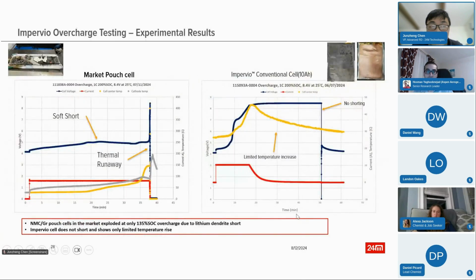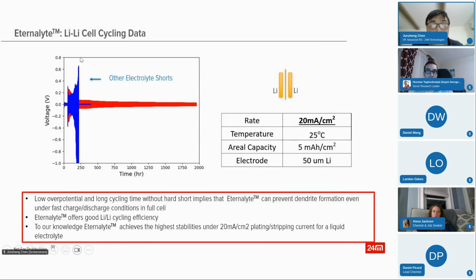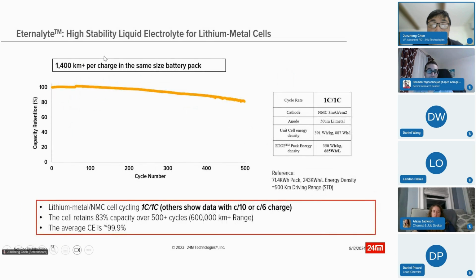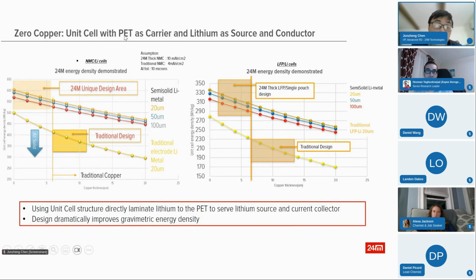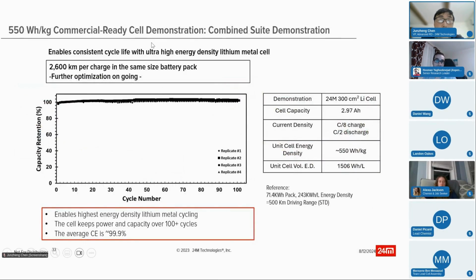Then we bring it to the lithium metal. We introduce one new electrolyte with a high current exchange number. That electrolyte can cycle at 20 milliamps per square centimeter charge and discharge without any short, and without dendrite growth. Then we demonstrate it in 1C NMC lithium charge-discharge continuous cycling for more than 500 cycles without any short. Then we take the copper away, and we use the lithium as the carrier and the current collector. Then we laminate lithium to our outside PET film and demonstrate a 550 watt-hour per kg commercial-ready, around 3 ampere-hour cell. And then that is around 4 cells together.